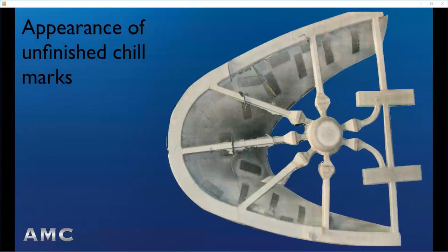But chills are very common in high specification air-set sand molds. The blending of chill marks is different than the blending of other process interface geometry markers. First, there's no cutting off of attached geometry. Depending on the fluid life of the alloy, the chill mark may have a thin raised fin of metal defining the edges of the chill as it was set in the sand mold wall. That thin fin needs to be ground flush with the surrounding as-cast sand mold profile.